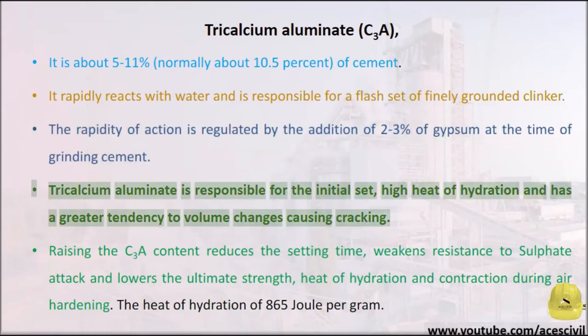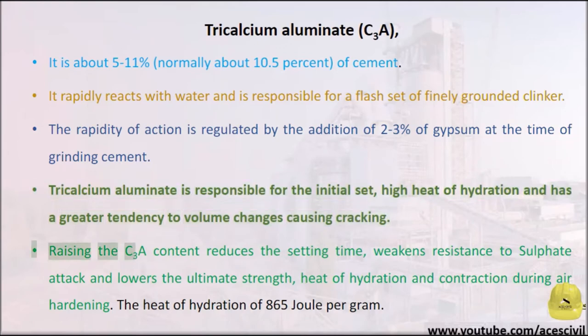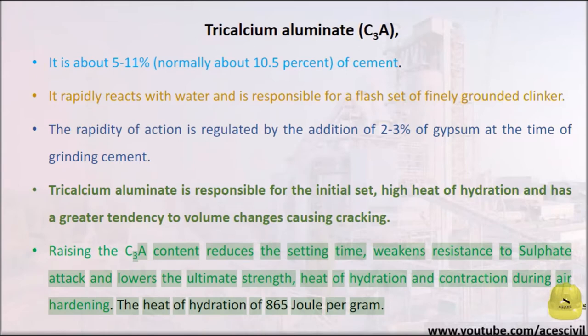Tricalcium Aluminate (C3A) is responsible for the initial set, high heat of hydration, and has a greater tendency to volume changes causing cracking. Raising the C3A content reduces the setting time, weakens resistance to sulfate attack, and lowers the ultimate strength.